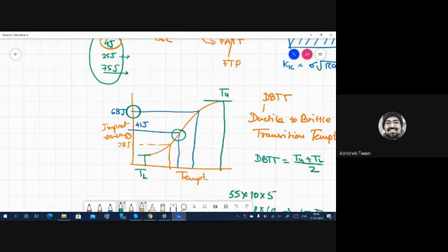I might also not achieve this energy if I'm doing an impact test on a grade of material which is BCC but still doesn't achieve a very high amount of energy. It is very brittle. I can have martensitic steel, which probably will always be brittle, a high carbon steel, or I can have cast iron, which will always be brittle.